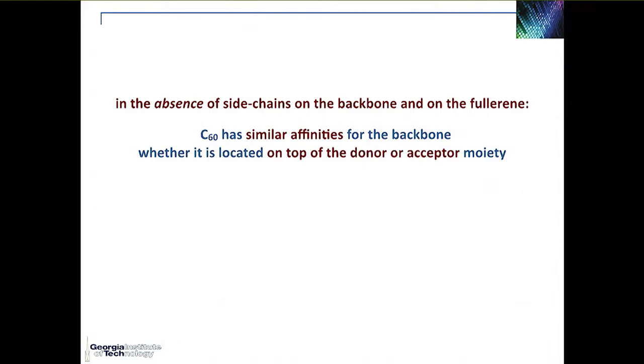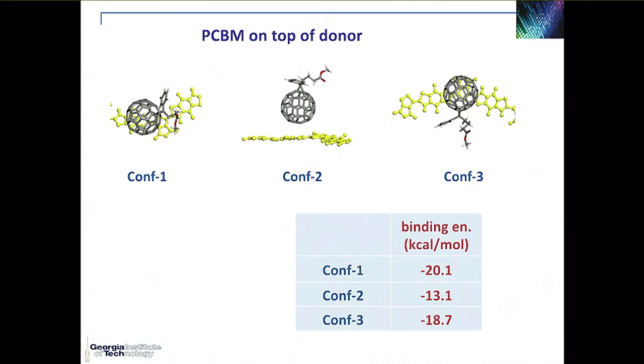So in the absence of side chains on the backbone and on the fullerene, what we learned is that the C60 has basically similar affinities for being on top of the donor or of the acceptor parts of the polymer, which means that the side chains must play a very important role. And in the next step, what we did is to consider side chains on the C60, so turning to C60 PCBM.